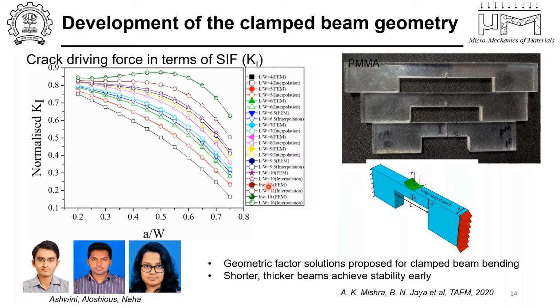And as you can see, there is a decrease in the normalized K1 with increasing a/W for small aspect ratios of these kinds of clamped beams. And this continues for L/W's of up to about 8. But beyond that, there is a slight increase in the normalized K1 before it tends to decrease again.